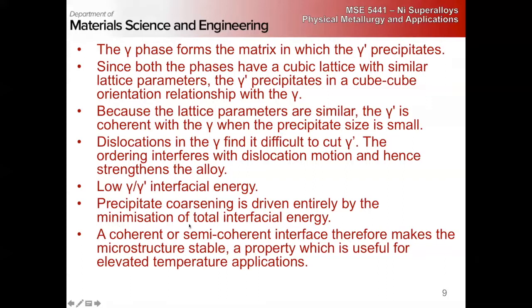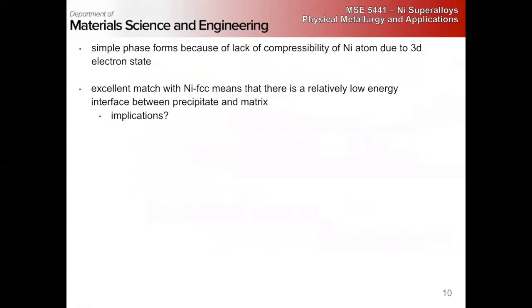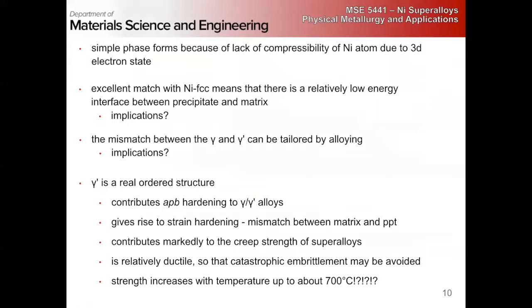Coarsening behavior is essentially just Ostwald ripening, driven entirely by the minimization of the interfacial energy, right? And this coherent interface makes the microstructure relatively stable, which is going to be useful for our elevated temperature application, right? Okay.